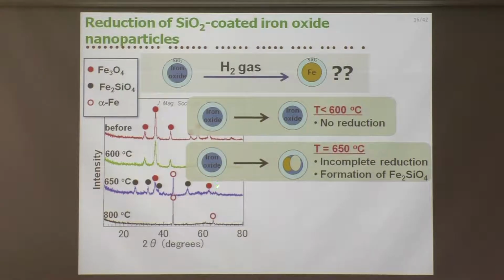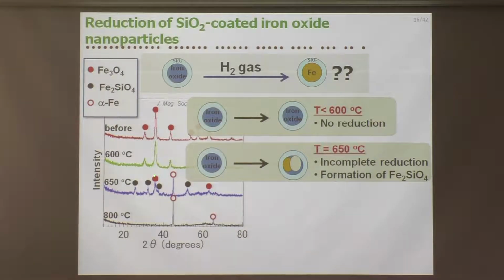However, as you can see, there still remains a diffraction peak from the starting oxide - namely, at these temperatures the reduction is incomplete. So we have to further increase the temperature, and at 800 degrees Celsius, now we can only see the diffraction peak from the alpha iron phase.